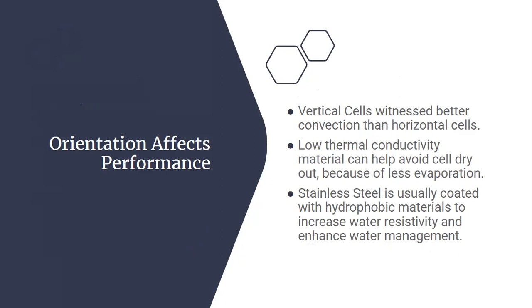So scientists have visualized the natural convection that we saw in the last slide. It was mainly around the cathode, using shadowgraphs, and they have measured the surface temperature of the gas diffusion layer and the accumulation of water at the cathode. They have found that the orientation of the fuel cell also played a big role in the speed of air convection and the oxygen flux in the electrolytic process.